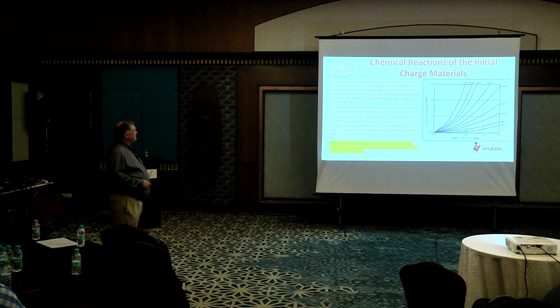I went to a foundry in Turkey that had a 30-ton furnace. They were putting 30% borings on the center cycle in the bottom, and wondering why they were washing out the taper section and floor so quickly. They had no idea what the chemistry was, first of all. It was wet, second of all, and it's quite aggressive with the oils. So anyways, charge sequence is important.